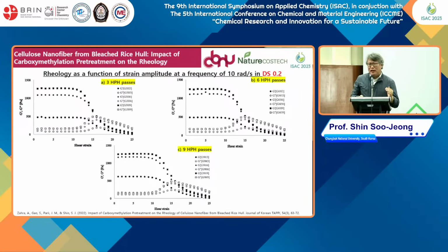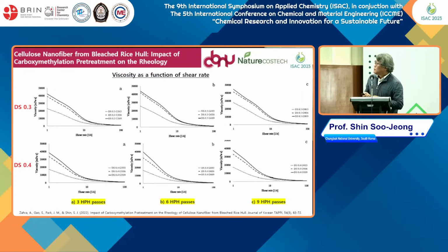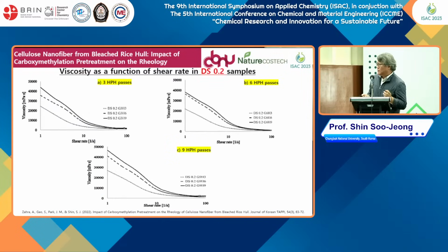Depending on the degree of substitution, and depending on the number of passes of the grinding or high pressure homogenizer, we can control all the different rheological properties. We made 3 passes of high pressure homogenizer, 6 passes, and 9 passes, and compared the properties. So at high degree of substitution, too much mechanical treatment means they decrease the viscosity and decrease the gel properties.